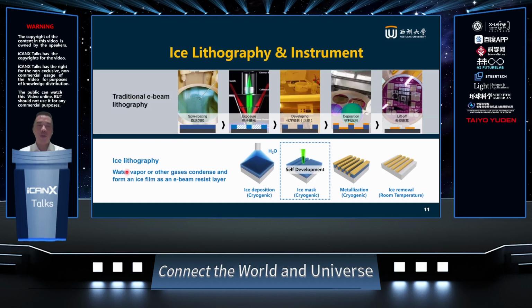So instead of using PMMA or ZEP and other resists based on polymers, we start to use water vapors to condense them at very low temperature and make them as a very thin layer of ice, a few hundred or a few tens of nanometers, and make the structure out of ice using electrons. And you can form structure directly.